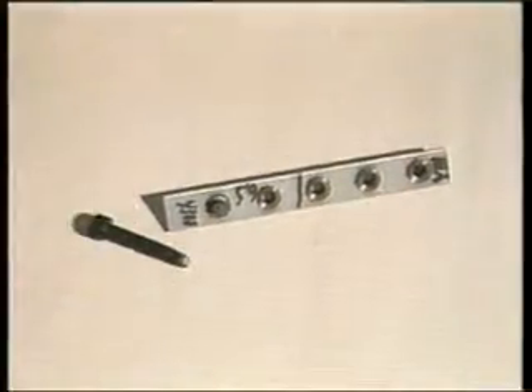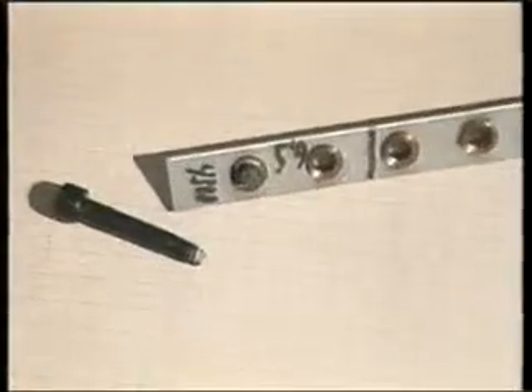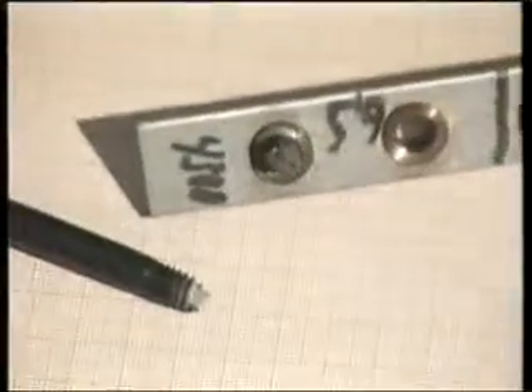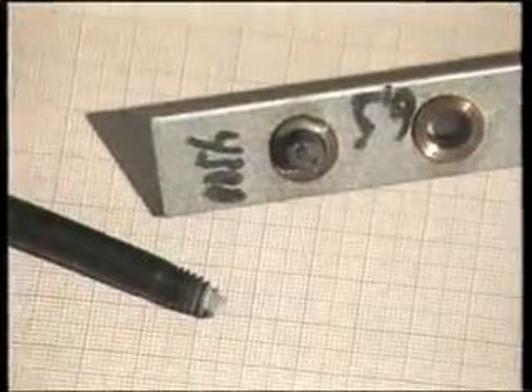In this test, the screw broke first. In further tests, the minimum strength of threads recorded was 9,180 pounds, exceeding the standard by 72%.